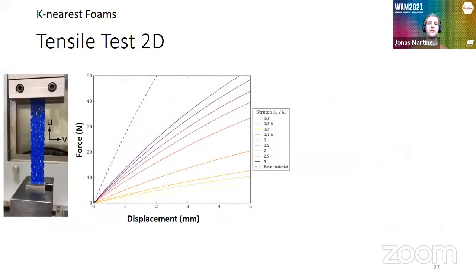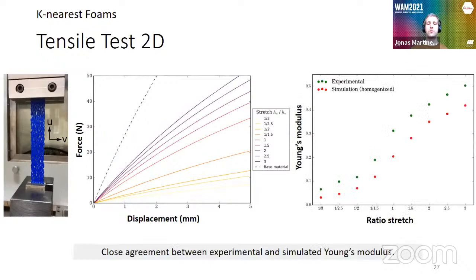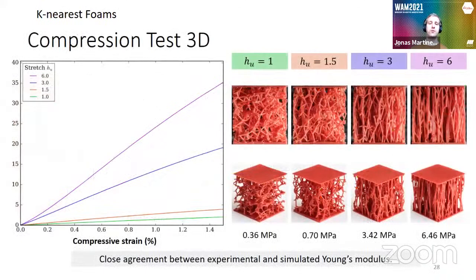We also did some tests with the help of people at Institut Jean Lamour, which is an institute of material science in Nancy, to verify the correlation. And we also got a close agreement between experiment and simulation. And we also did some 3D tests. As you can see here on the right, you have a structure that basically tends to have more struts aligned to the vertical direction. And of course, this implies a higher Young modulus in this direction.